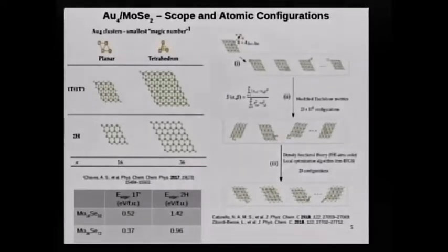The first step is to generate the adsorption probable structures by randomly adsorbing the gold cluster on the surface of the nanoflake, then taking this huge set, which has been considered with 20 million configurations, comparing them by the modified Euclidean matrix, and reducing them to the 20 most dissimilar configurations, and then taking this reduced set and performing the DFT calculations.